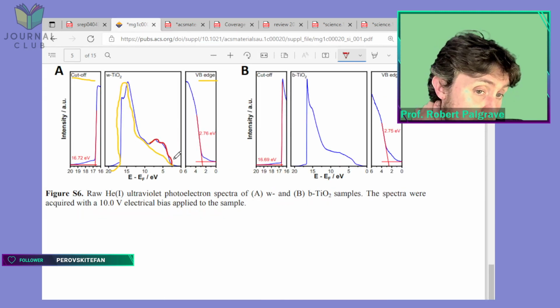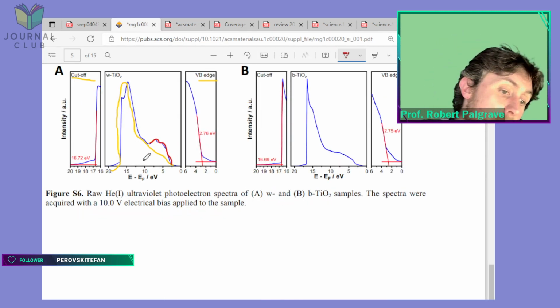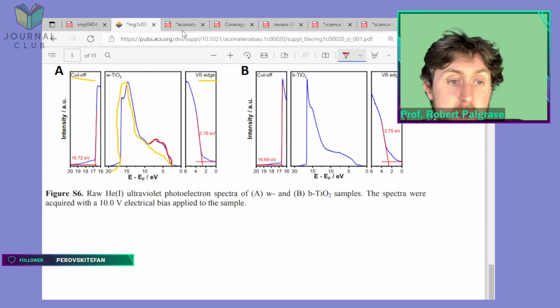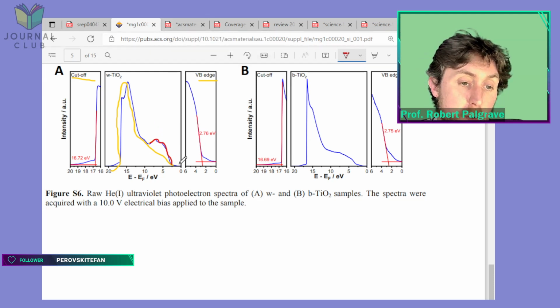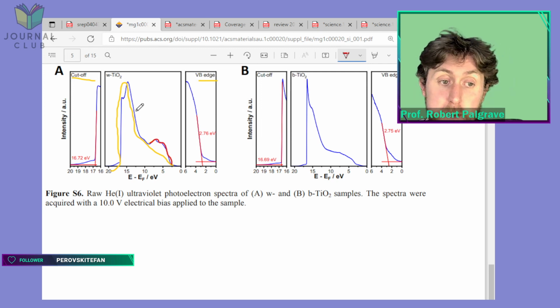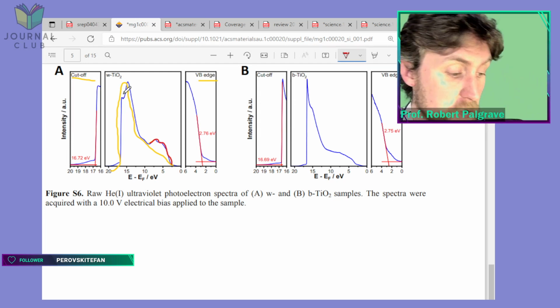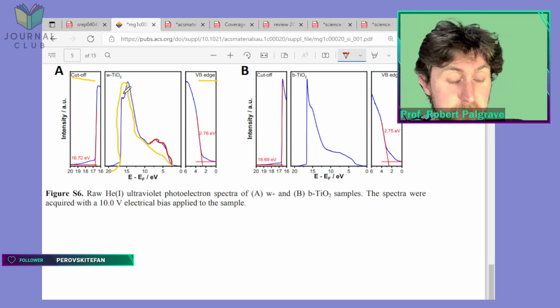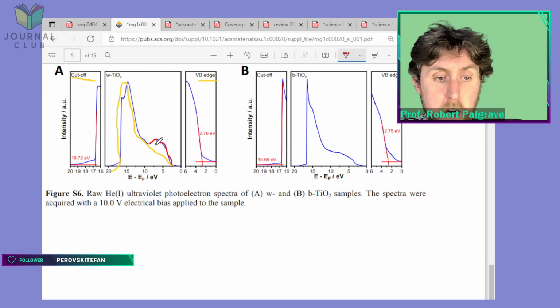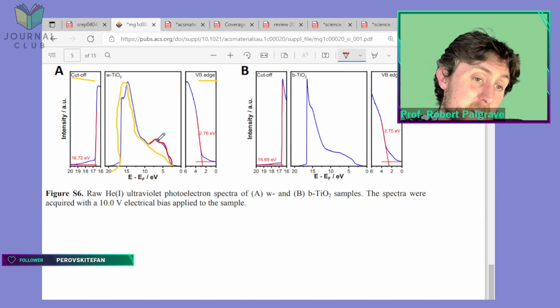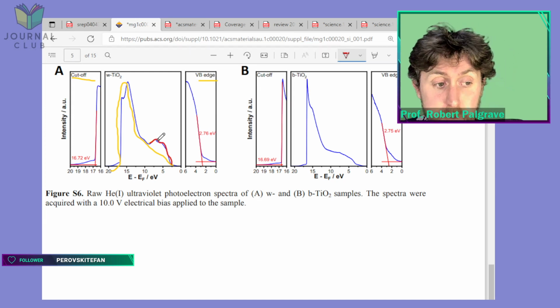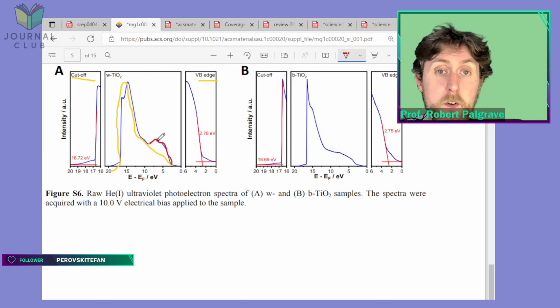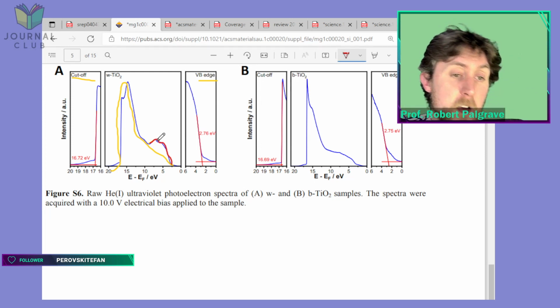They took their UPS spectrum and they subtracted a background. Now, how did they decide what background to subtract? Well, they used something called a Tougaard background, which is one way of doing this, but there are lots of other ways of doing it. Tougaard is one of the background functions which is most strongly based on some kind of physical phenomenon, on actually thinking about the physics of what's going on there, but it's still difficult to do. There's lots about the background, especially the secondary electron background that comes out, which is to do with things that are very hard to control, things like the morphology of the surface, the curvature of the surface, the roughness of the surface.